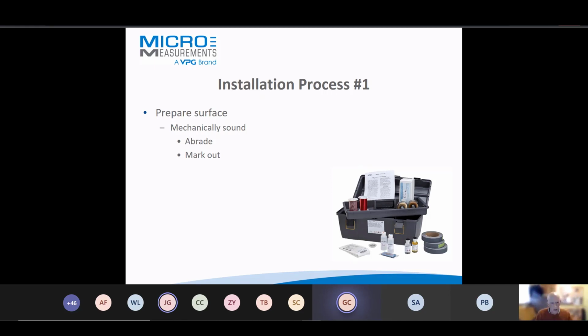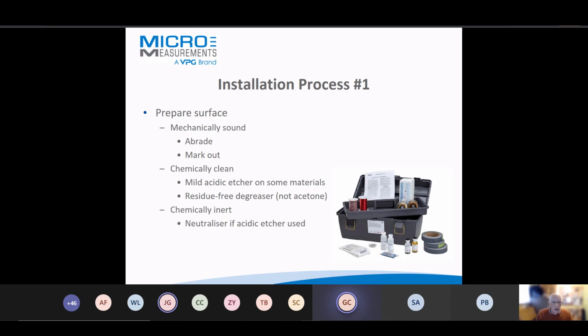So we're going to abrade back to base metal. We're going to provide some sort of marking out so we know exactly what position to put the gauge. We're going to follow that with some chemical cleaning. Some materials use an acidic etcher, very mild phosphoric acid. Perhaps use some sort of degreaser, avoid acetone or degreasers that leave a residue. And then we make sure that we reach neutral pH on the surface as well. So if you use an acidic conditioner, you must use a neutralizer for optimum pH for letting the adhesive bond to the surface. So that's preparing the surface.